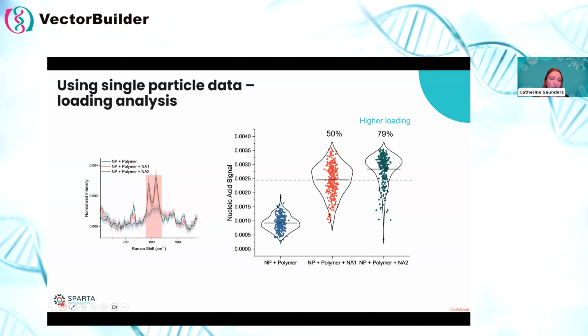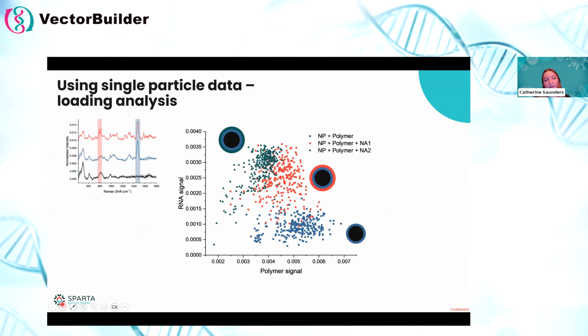So this is if you want to do the more straightforward analysis. What we can also use is the fact that, of course, we have measured all of this different chemical information. So we can then start to move to bivariate plots where we're adding in extra parameters to understand the relationship between different components. So what you can see here is a bivariate plot. This is really showing you the relationship between the polymer signal, so your coating, and your loading. And you can start to see here subpopulations forming and also the distribution of these different components.